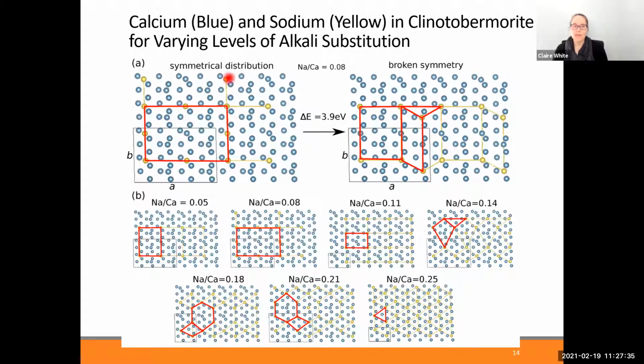One that has a very symmetric distribution of sodium in yellow versus the calcium in blue, where these are all the calciums in the system. And over here, there's some broken symmetry that's been incorporated. And actually, there is an energy penalty associated with a broken symmetry that's almost 4 electron volts relative to the structure.